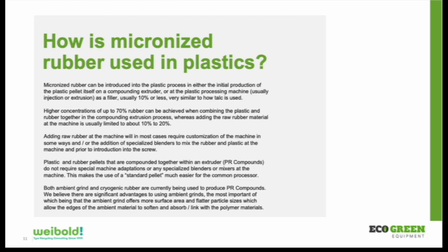But adding the rubber at the machine will most likely require customization of the machine in some ways, and or the addition of specialized blenders to mix the rubber and plastic at the machine. So again, what I'm saying is if you're taking the raw rubber and trying to introduce it at the machine, you're either going to have to change your screw configuration in that injection molding or blow molding machine to get a better mix of the material, or more than likely you're going to mix the material very well in a volumetric or a weigh scale blender, which is mixing the additives, the plastic, the rubber, all at one time into the screw. So it usually requires some tweaking of the process.